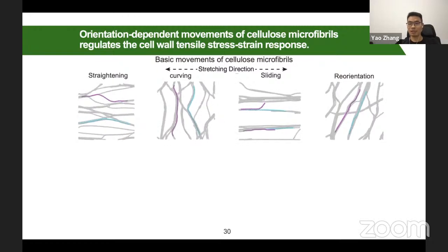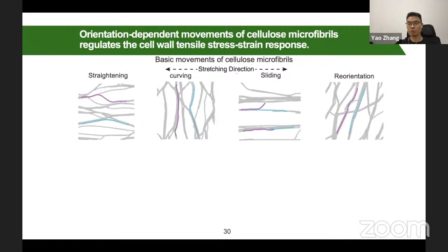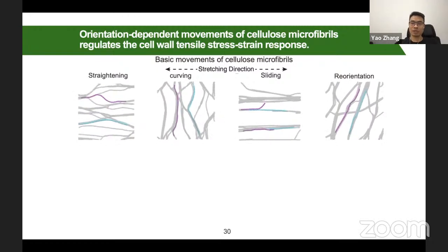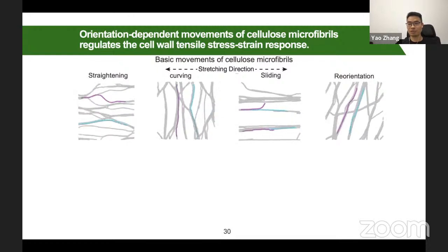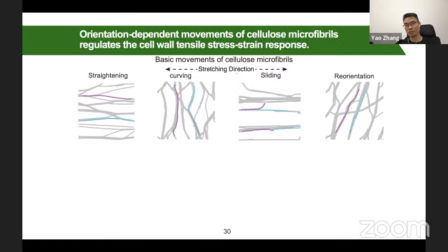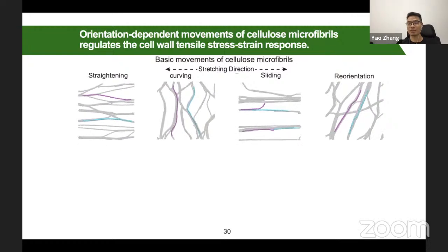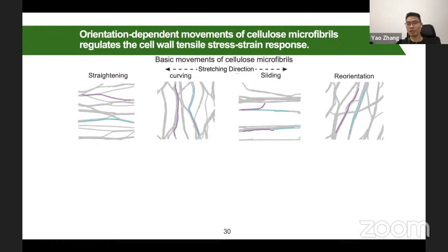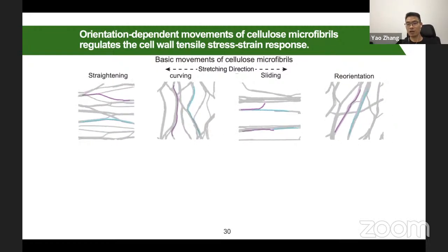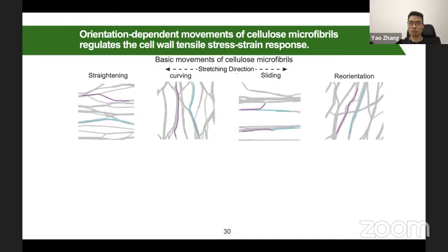The first one is the reorientation. So when you stretch your cell wall, some fibers begin to rotate. I think the rotation direction is such that after you rotate, the orientation of the fiber is closer to your strain direction.